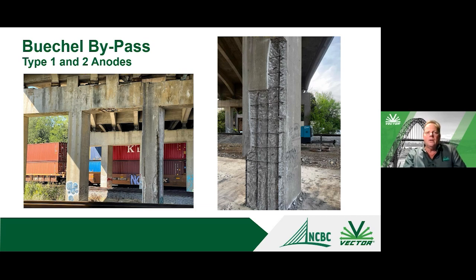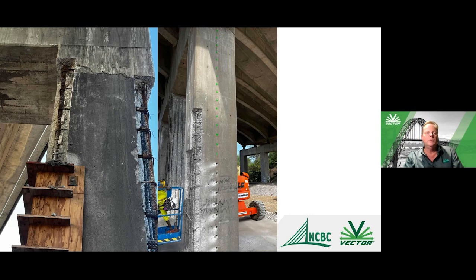This is a project where you had a chloride contaminated substructure, and obviously you have corrosion that's occurring, causing concrete delamination and spalling. And then this bridge is over the rail track. So just working with the railroad, they want to make sure that they don't have to go back and repair the structure anytime soon. So there's an additional investment beyond the repair just to provide some additional corrosion mitigation.